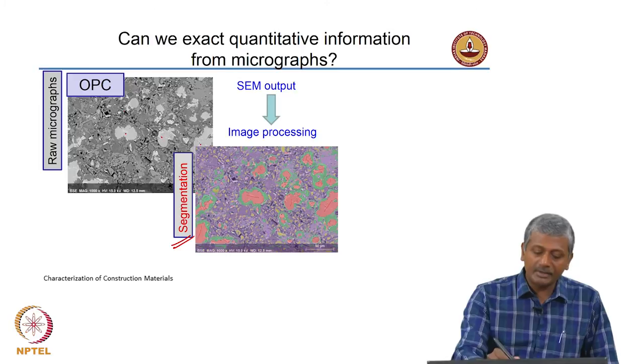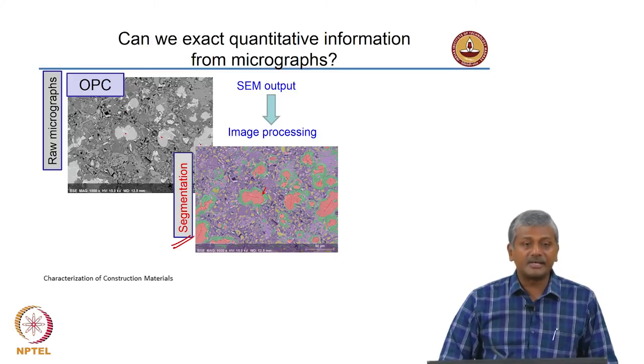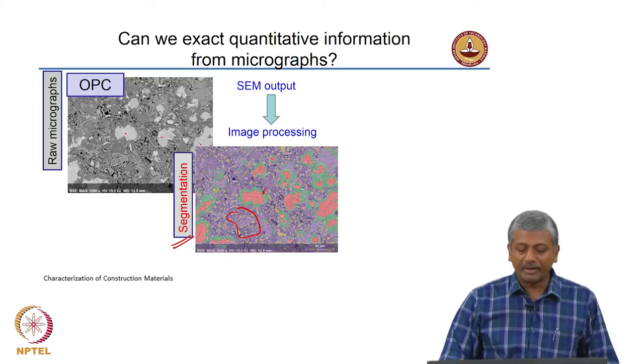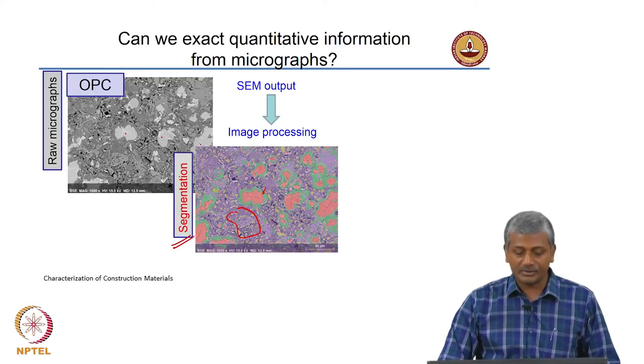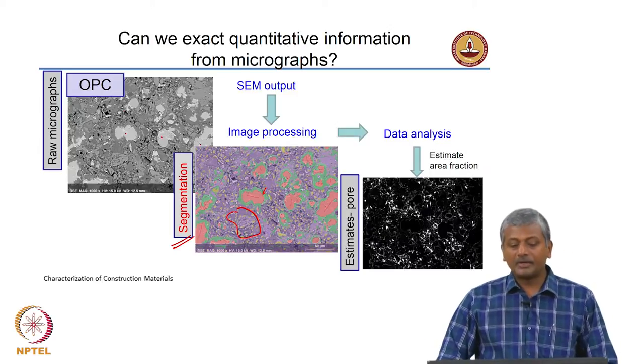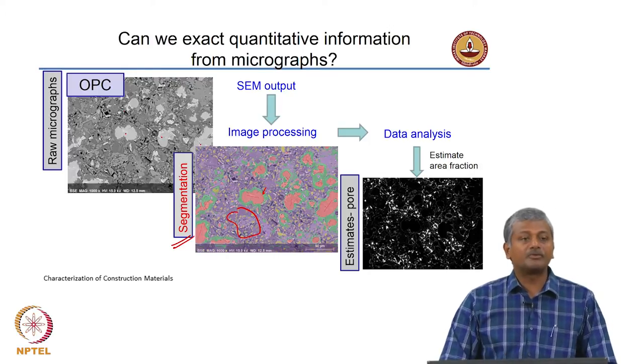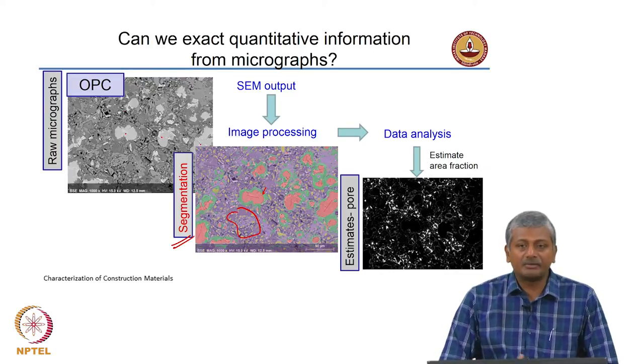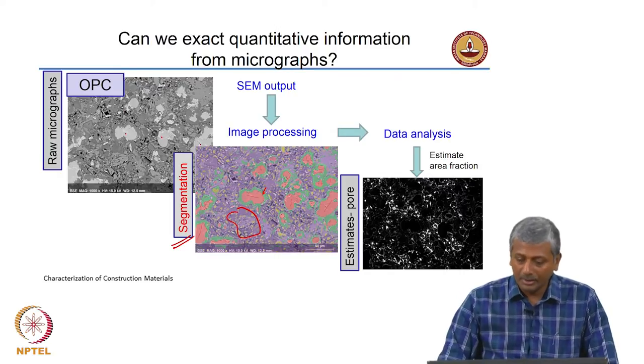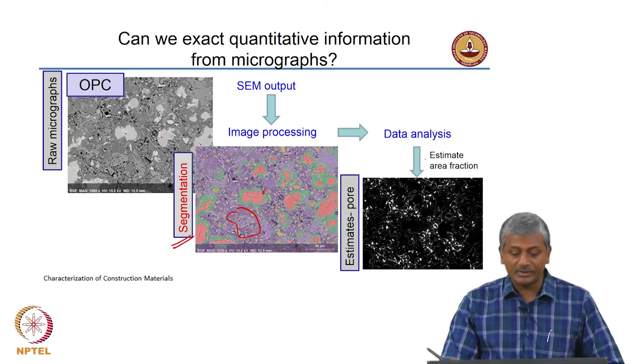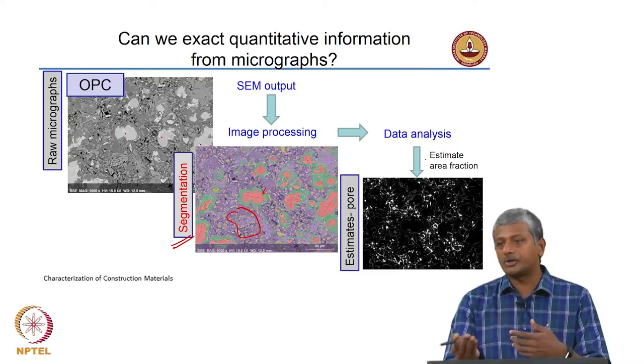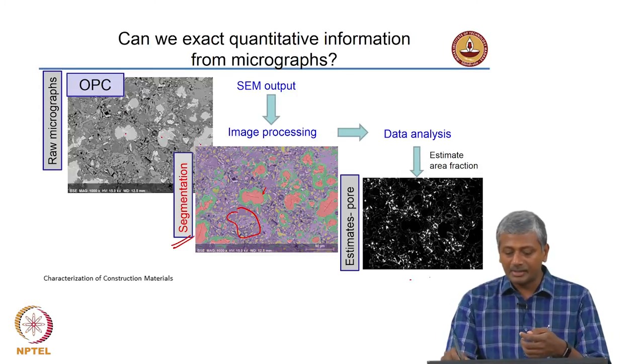You can see that the unhydrated grains are now pink, the inner C-S-H is green, the outer C-S-H is a violet-indigo color, and the pores remain black. Other shades of blue and violet govern other phases like calcium hydroxide. For data analysis, you can count the number of green dots and get an estimate of the amount of inner C-S-H in a given volume. For area fraction of porosity, you can binarize and give black to all others and white to all the pores, or work with the negative image. This way you can get an estimate of the porosity.